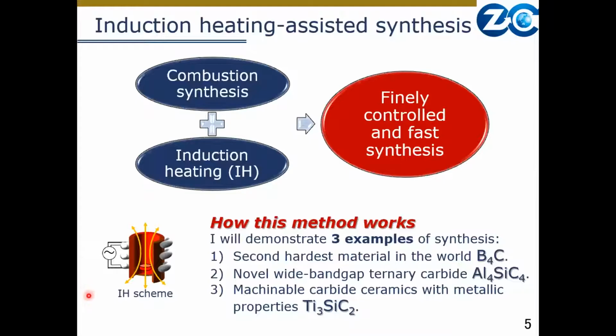Induction heating technique is a well-matured method to heat materials. The scheme is shown here. Induction heating is based on passing an alternating current through a coil, and then an electrically conducting object put inside the coil is heated up contactlessly and very fast. Moreover, with induction heating, we can control heating rates in a very wide range. As a result, through combination of combustion synthesis and induction heating, it's possible to design finely controlled and fast synthesis.